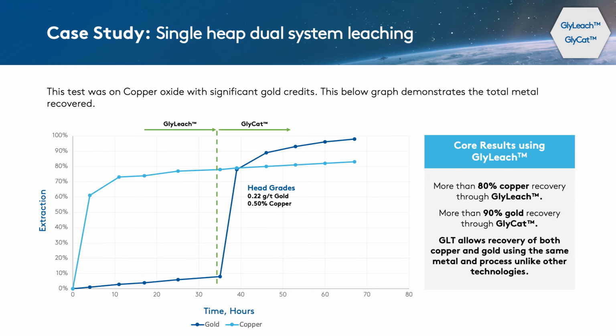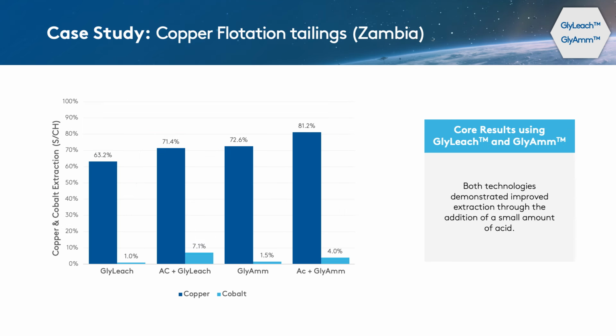The second example is a single heap dual system leaching. This test was done on copper oxide with significant gold in it. The head grade shows 0.22 grams per ton of gold and 0.5% copper. We did this in two stages. Stage one was the GlyLeach. We did it to extract the copper, and we were able to extract around 80% of the copper during 35 hours of leaching. After that, we introduced cyanide to the system to extract the gold, and we reached around 90% gold extraction.